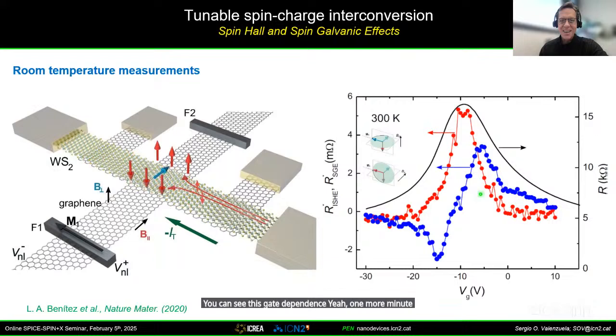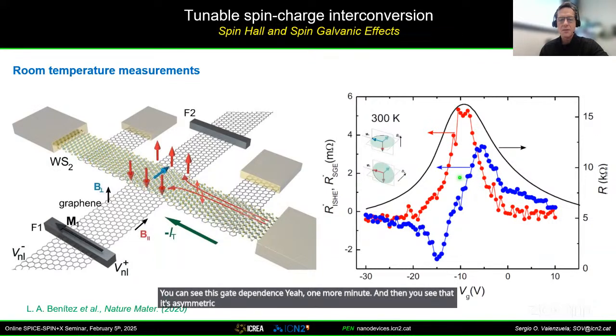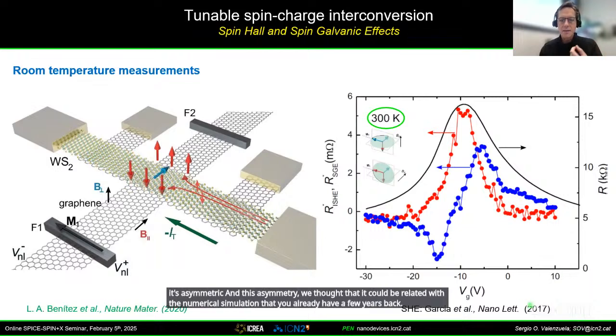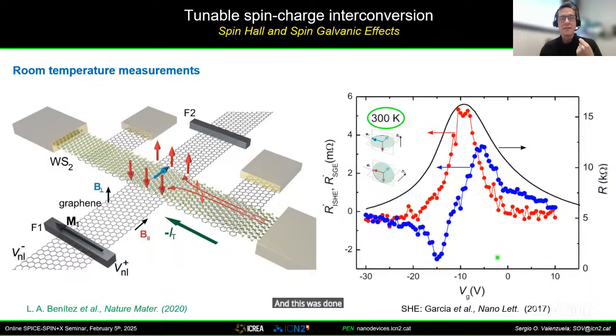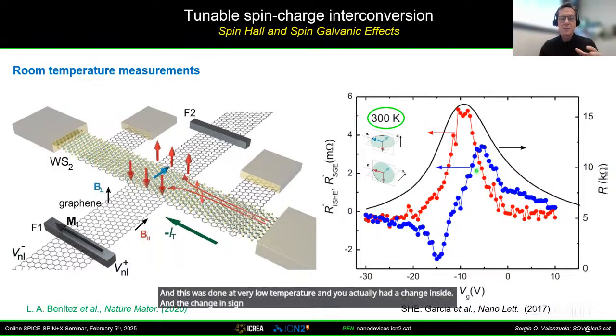And then you see that it's asymmetric. And this asymmetry, we thought that it could be related with the numerical simulation that you already have a few years back. This was done at very low temperature, and you actually had a change in sign. And the change in sign, because it is done at room temperature, can be actually smeared out. And that was the hypothesis.